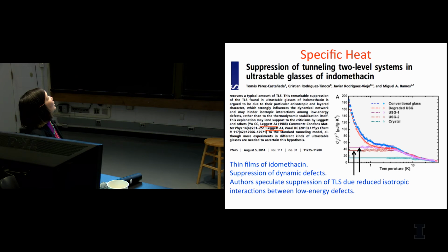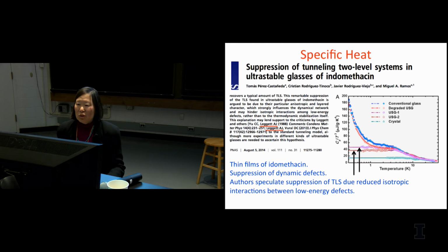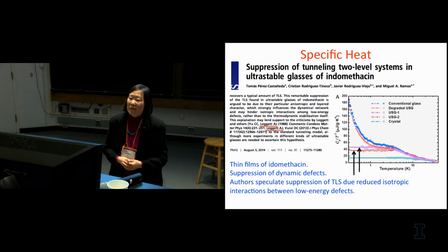So one case is indomethacin, which is some organic compound. They make thin films of it, and if they plot C over T cubed versus temperature, so remember that for a glass, the two-level systems or whatever show up as this tail here, and in these indomethacin thin films, they don't see that. And so there's a suppression of the two-level systems. In fact, they cite Tony's papers in their abstract, and they speculate that maybe the suppression of these low energy defects is due to a reduced isotropic interaction between the defects.